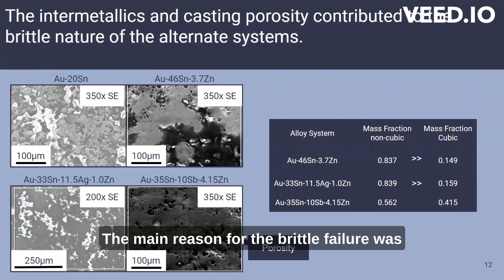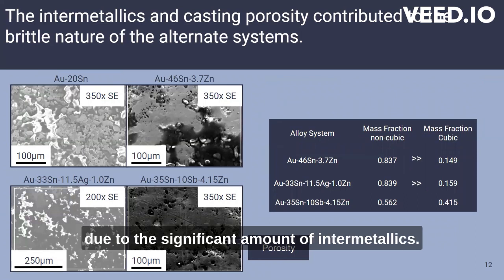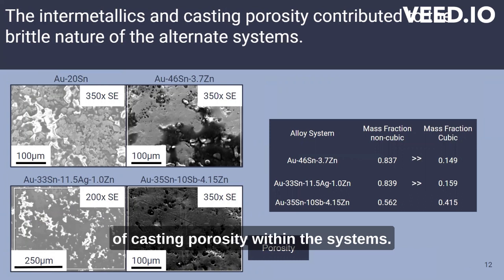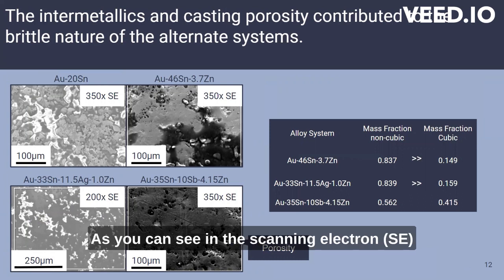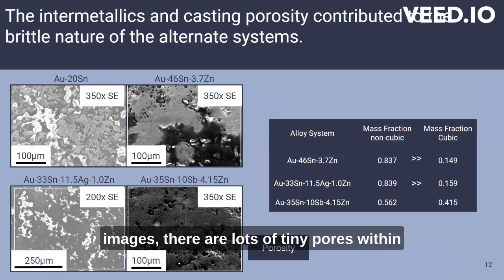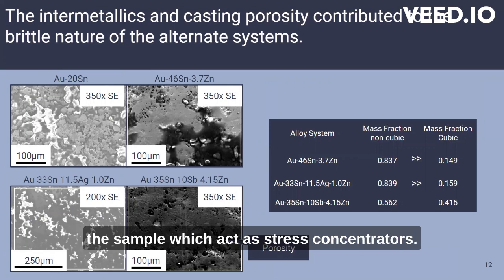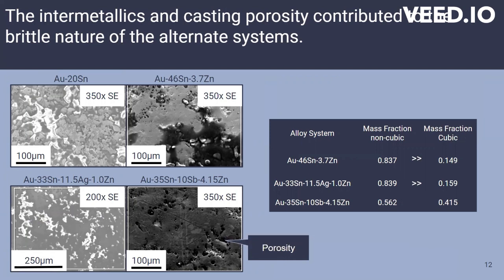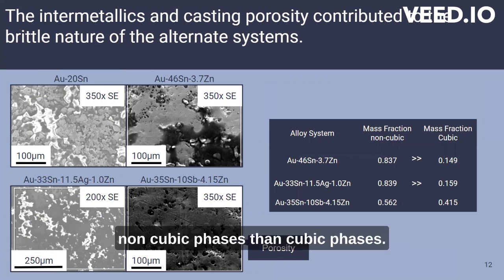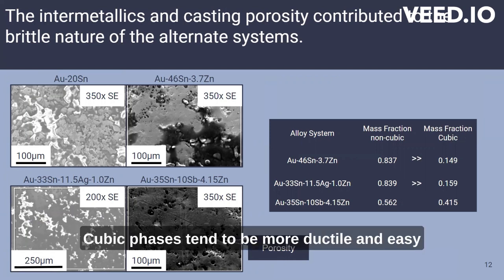The main reason for the brittle failure was due to the significant amount of intermetallics, and then there was also significant amounts of casting porosity within the systems. As you can see in the scanning electron images, there are lots of tiny pores within the sample, which act as stress concentrators. And then there are also significantly more non-cubic phases than cubic phases. Cubic phases tend to be more ductile and easy to work with compared to non-cubic phases.